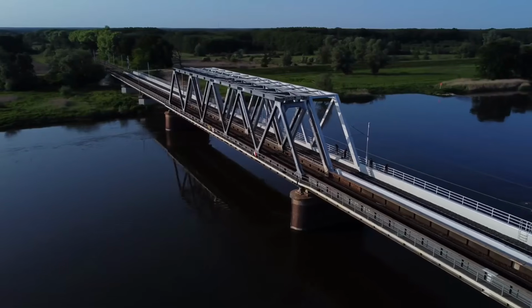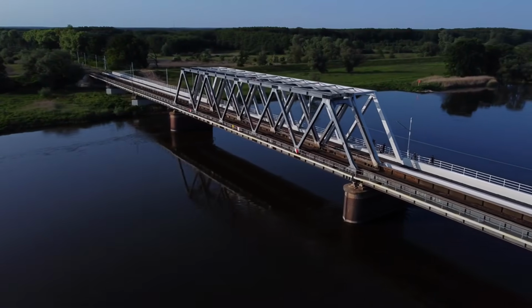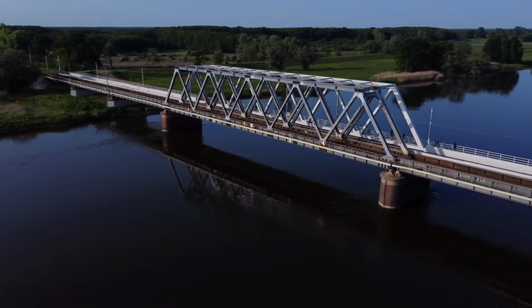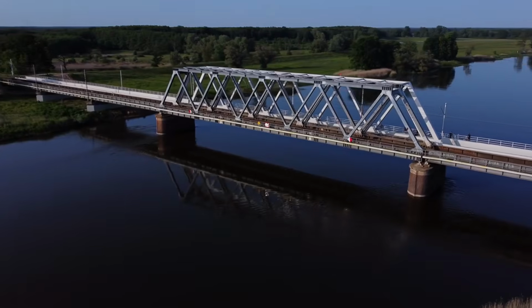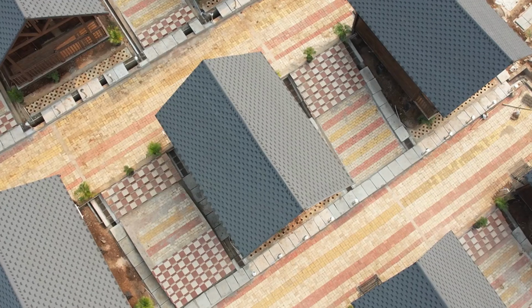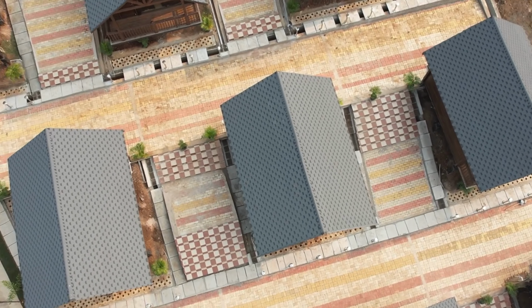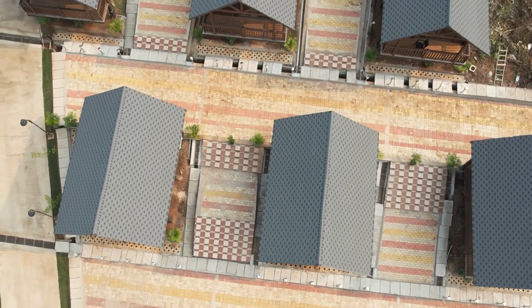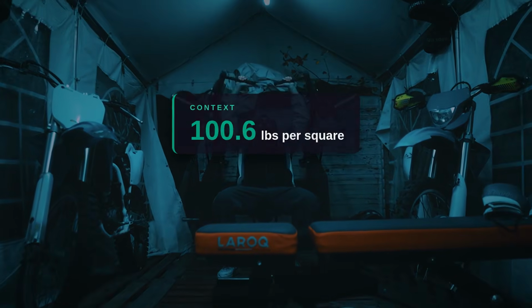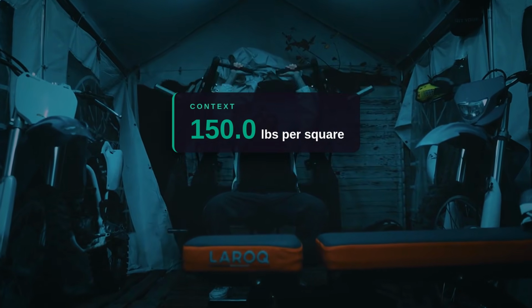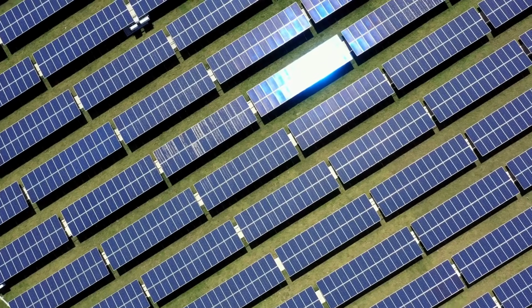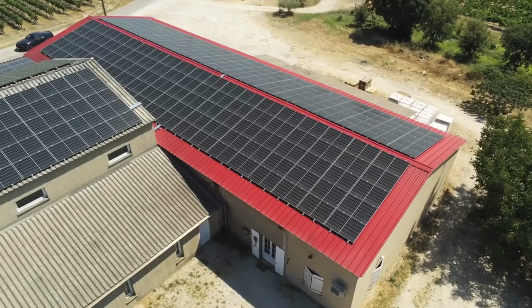Now here is the twist that changes the calculus for a meaningful segment of the housing stock. Over the past 20 years, a category of product has matured that solves most of the weight problem while preserving the thermal and mechanical benefits of a profiled tile system. Stone-coated steel tile roofing, the most well-known brand being Gerard, but with multiple competitors now producing comparable systems, uses a lightweight steel substrate coated with a layer of ceramic-bonded natural stone granules, formed into profiles that mimic traditional barrel tile, shake, or flat tile geometry. Stone-coated steel tile weighs 100 to 150 pounds per square, roughly 1/7 the weight of traditional clay tile. It can be installed on virtually any roof framing system without structural modification.